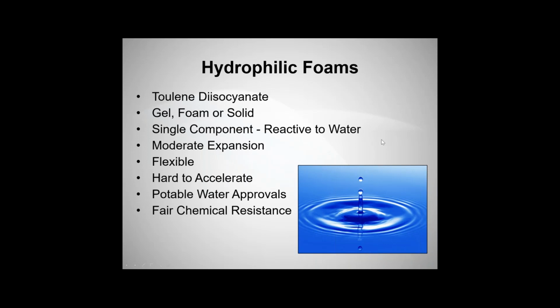Tend to have moderate expansion and are flexible, which is great because when we're doing localized grouting, which is predominantly what urethane foams are used for, in flexible situations it allows those components to move and still maintain water resistance or water impermeability. They are harder to accelerate, but there are potable water approvals and they have a fair chemical resistance.